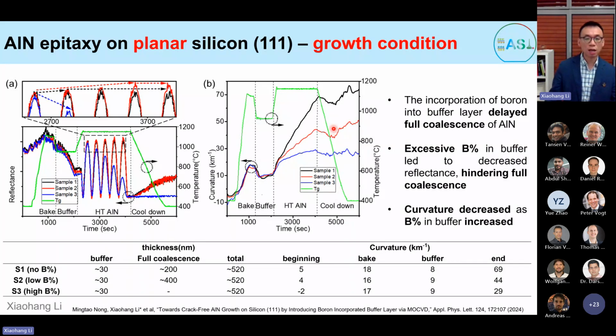As you know well, we can get a lot of information from those in situ data. Basically, we found that when we incorporate boron, from the reflectance measurement, we can delay the full coalescence of aluminum nitride. In addition, by having boron inside, we can also reduce the curvature significantly, as you can observe here. Sample 3, with the highest flow of boron, reduced the curvature by the most.